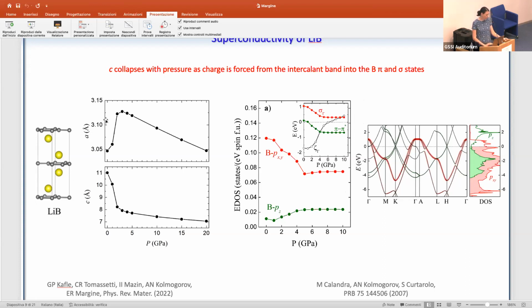So here I'm showing what happens in our calculation. You can see that the interlayer distance collapses quickly, and then there is a small increase of the in-plane boron-boron length followed by a decrease. What we found is that although in this material the van der Waals interaction doesn't play a very important role, there is still a small shift in the pressure that describes this transition between two regimes. In the original study, no van der Waals functional was included, so the transition pressure was found to be 5 gigapascal. If you include the van der Waals functional, you will find that the pressure point decreases to 3 GPa.